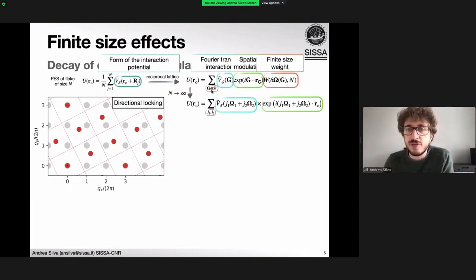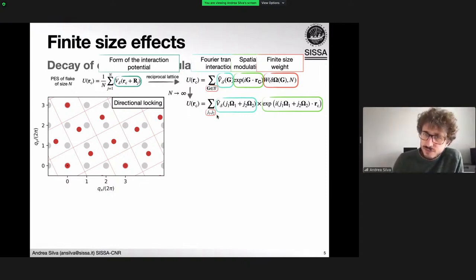So all the Fourier components, which means any possible modulation of the corrugation, enter the system, but they are weighted by the specific shape and size of the flake. And in the infinite limit, this needs to give back the categorization I explained before, because this weight will just select the relevant Fourier component, which here are these matching vectors defining the moire pattern of the system. At finite size, all other components can contribute as well.